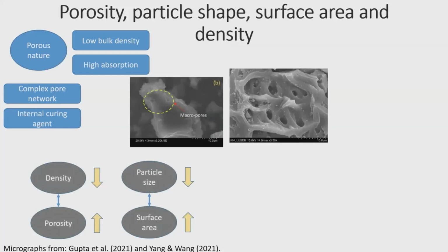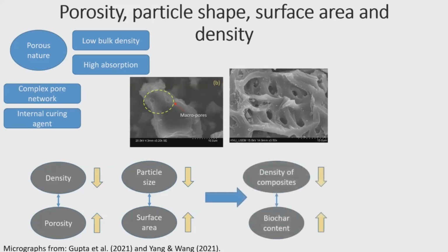This means that while porosity, surface area, and density are important properties for cementitious composites, these properties are linked. For example, density is related with porosity. As porosity increases, density tends to decrease. The same thing happens with surface area. When particle size is decreasing, surface area tends to increase.